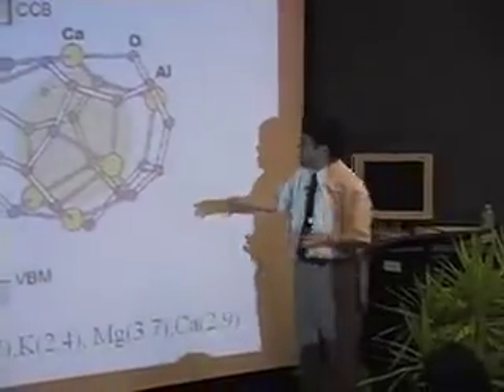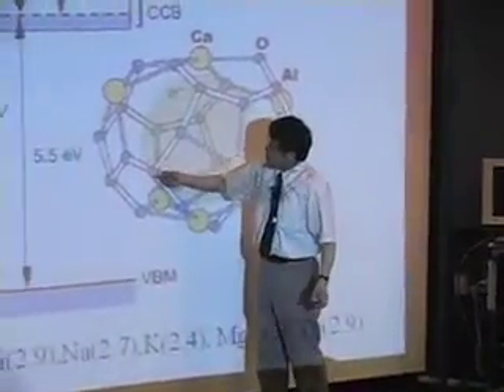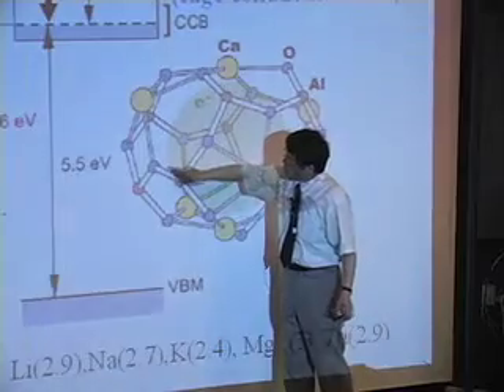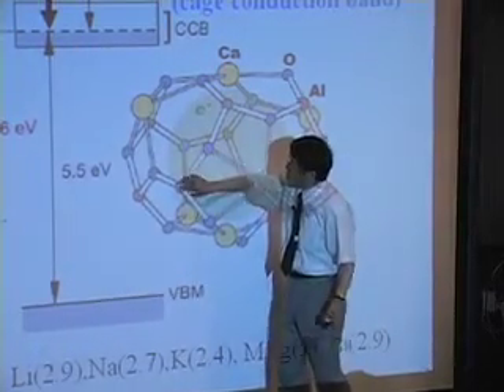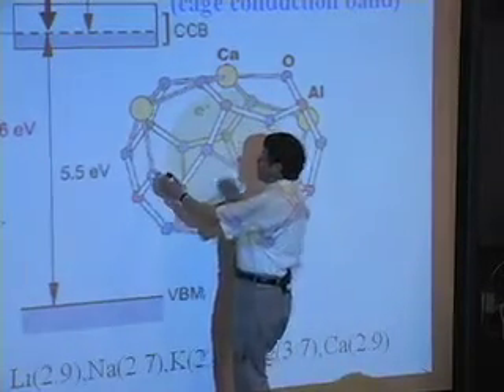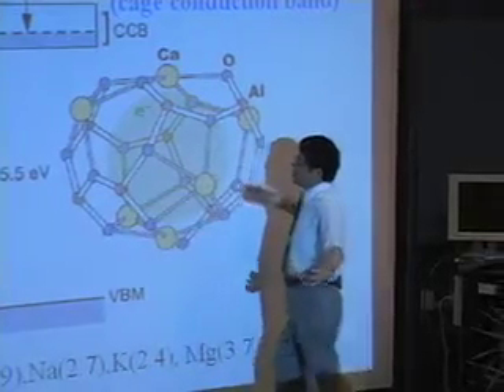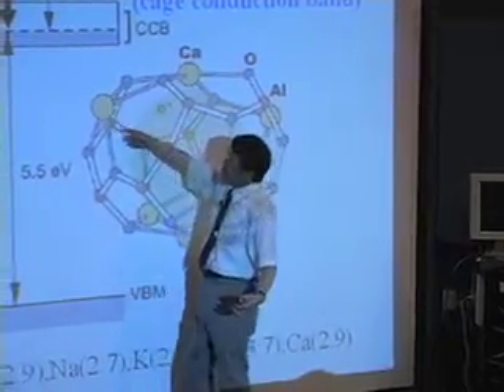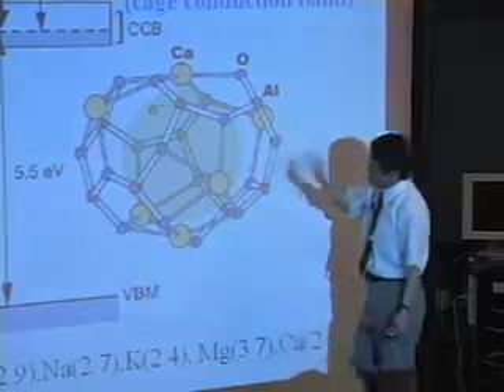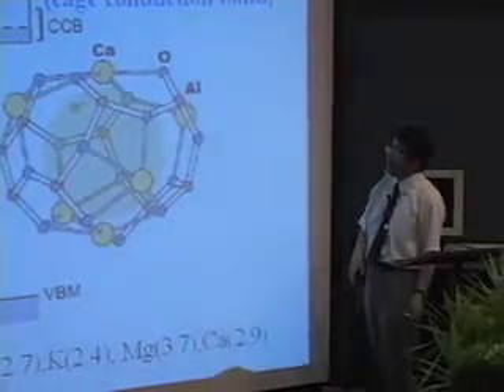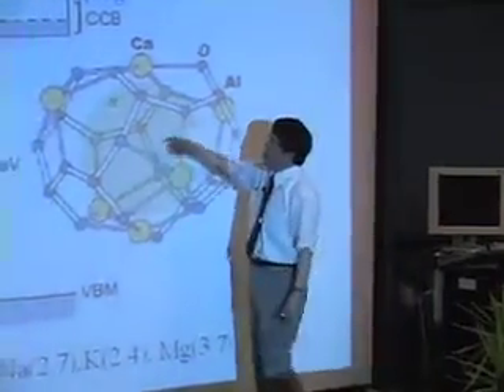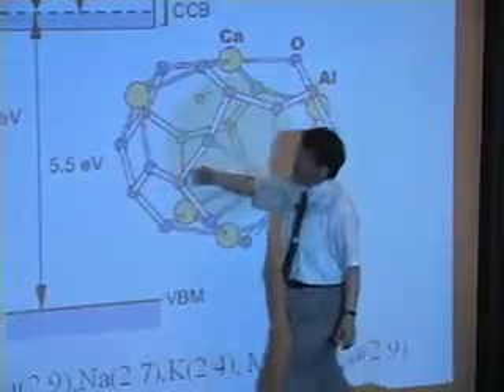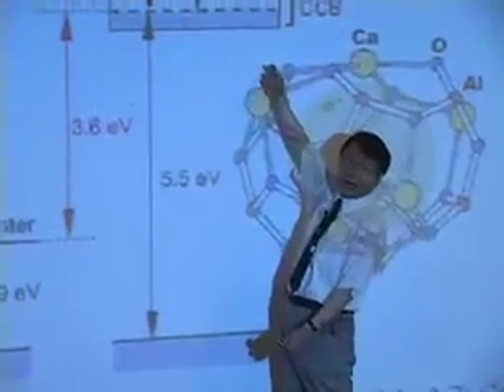This is due to the strong tetrahedral aluminum bond, which is pretty strong. Aluminum 3 plus stretches the oxygen and calcium ion. So such a structure is pretty uncomfortable for the electron. That's why this level is pretty high.